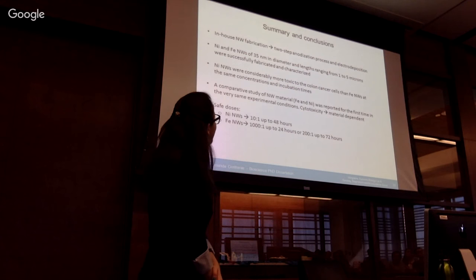Okay, I will wrap up and conclude. So as a summary, first I showed you how we were able to fabricate nanowires here at KAUST. We use a two-step anodization process followed by electrodeposition. We successfully fabricated and characterized nickel and iron nanowires of 35 nanometers in diameter and lengths ranging from 1 to 5 microns. Nickel nanowires were considerably more toxic to the colon cancer cells used than iron nanowires for the same concentrations and incubation times. That makes iron a more appealing material for biomedical applications.